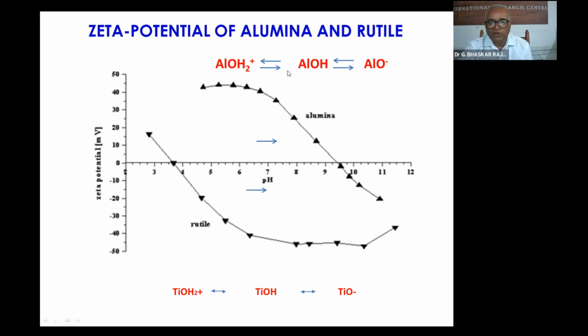Similarly, the zeta potential of alumina. When you take the measurements, at this pH, around 9.7, alumina is in the form AlOH. It is neutral, neither negatively nor positively charged. Below this pH, it is in the form of AlOH2 plus, and beyond this pH, it is in the AlO minus form. So why I am talking about this is, if you want to adsorb, you can change the surface of this alumina into different forms. If we know the PZC of this particular alumina, we can predict.